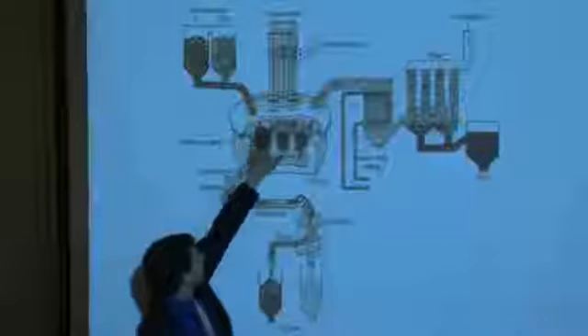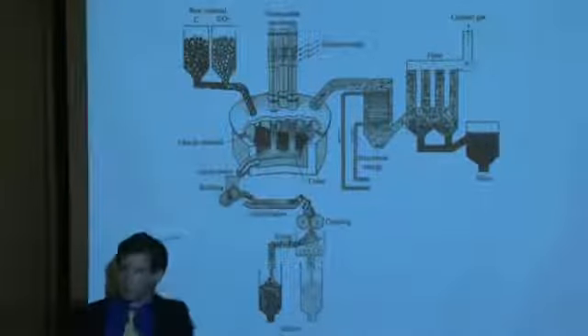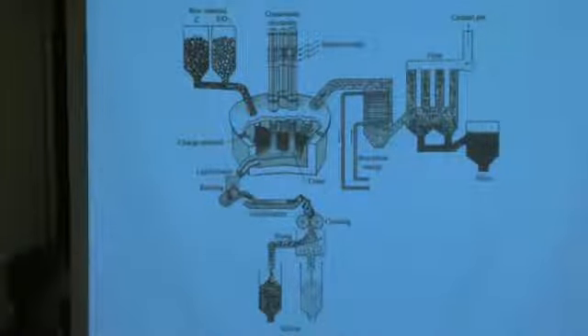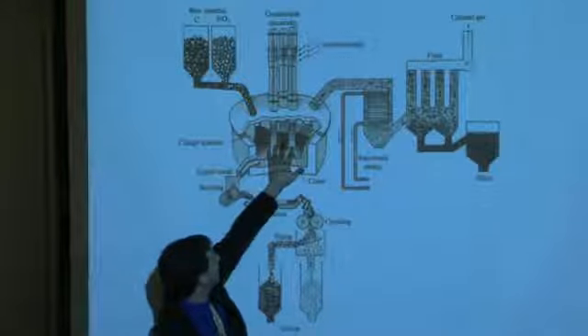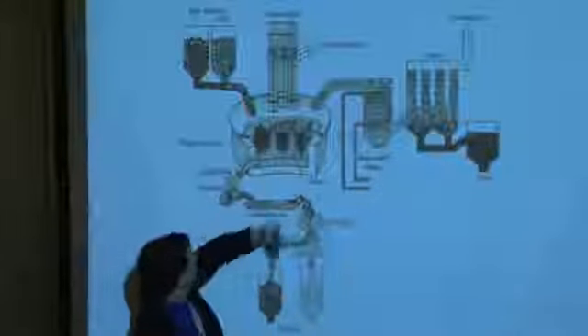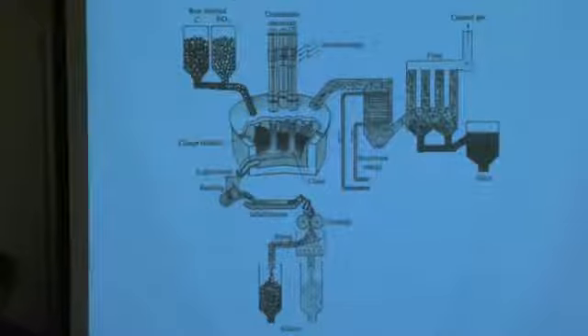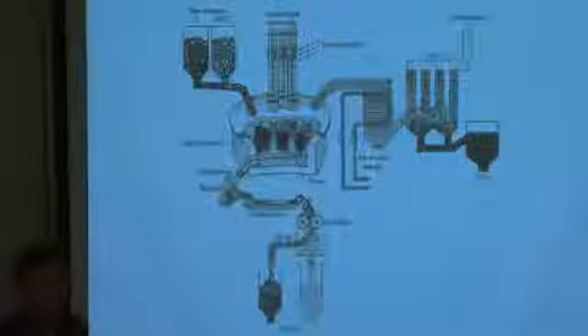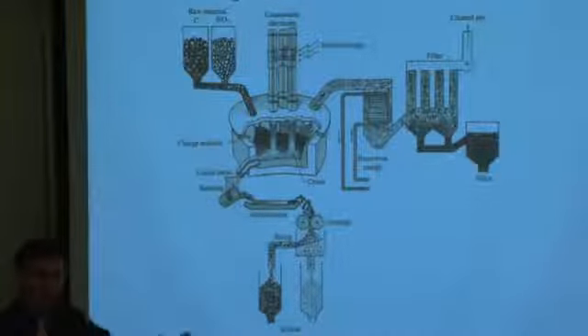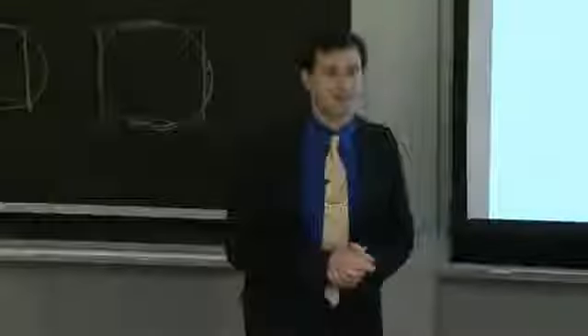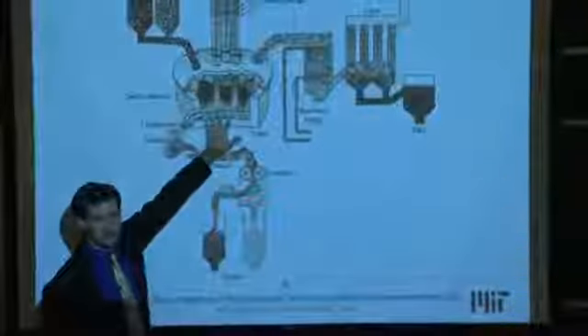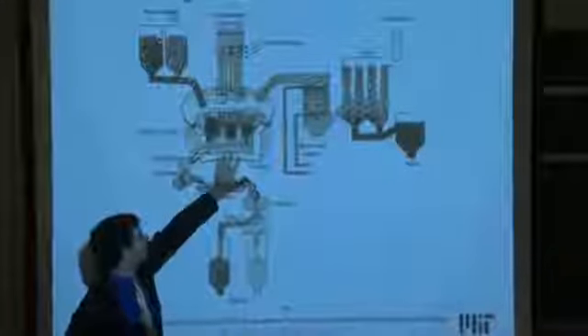And what's happening is these feedstock chunks are being thrown in at the top, and there's an arc going between the electrodes, usually some carbon-bearing material, and a base contact. And so that arc creates a very high temperature, something on the order of up to 2,000 degrees Celsius near the arc. And the temperature decreases as you go further and further away. So up near the top here, it might be even below the melting temperature of silicon, somewhere around 1,200 degrees. So this is an extremely inhomogeneous, messy system, this metallurgical grade silicon refining furnace right here, this arc furnace,